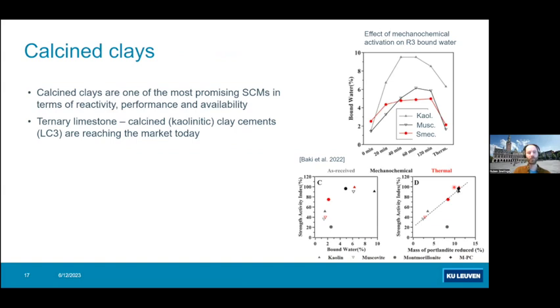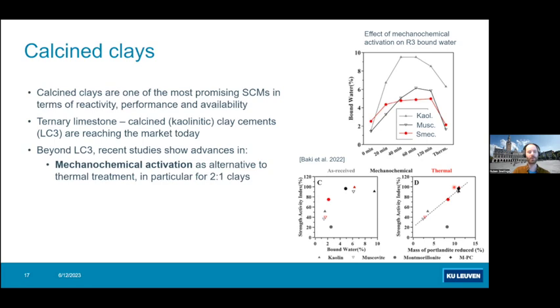Calcined clays are one of the most promising SCMs in terms of reactivity, performance, and availability. And we see that these ternary mixes of limestone and calcined clay cements are really reaching the markets today. Perhaps not in Sweden, but in Denmark, in Belgium, in France, in many places in Western Europe, we start seeing the first limestone calcined clay cements reaching the market. So this is to some extent already known.